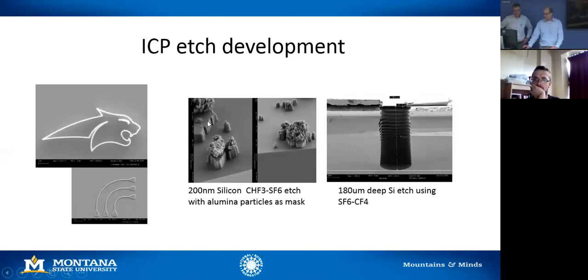You can see here, this is the top surface of the wafer. Then we etch down 200 nanometers. It's a little rougher, but it's hard to tell the difference. You can see how steep the sidewalls are. So anywhere where it's shadowed at all, it's very directional, and it's a very smooth etch. So that's at the nanoscale, we can do that.